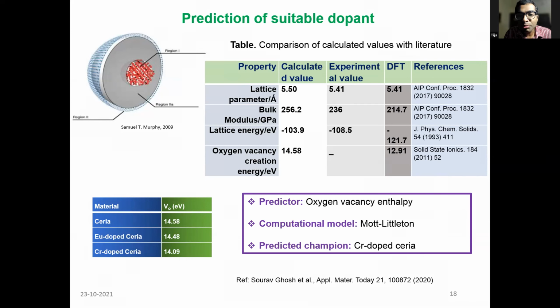And in fact, these computations are something like 10 times faster than conventional all electron calculations and so on, because as I said, this is in the classical regime. And what we found is that we get enthalpies that are close to what would be otherwise predicted by DFT and so on. And wherever there is an experimental value, we are within plus or minus 1 electron volt in terms of accuracy.